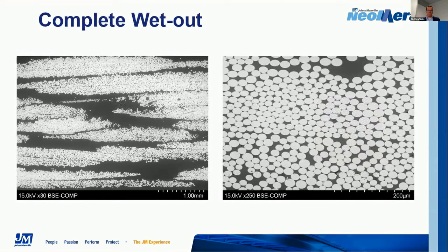So just to give you a view, here's an SEM photo of a cross-section of some material that we've produced. And what you really see is just the full wet out and encapsulation of all the fibers with the polymer. It does a really good job of getting into all those different spaces within the composite. This is really hard to do when you have a higher viscosity system. And that's all essentially virgin AP nylon polymer. So it hasn't gone through any thermal cycling. So it's going to process very well and won't have that history that you would see in a melt impregnation process.